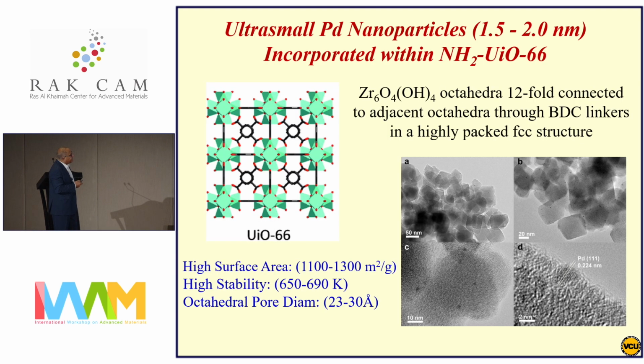And this is a MOF that we used to incorporate palladium catalyst. And we immediately see that when we do this by laser reduction, also on the MOFs, we produce very small particles of palladium, 1.5 to 2 nanometer particles. This is the MOF itself, and these are very tiny palladium particles.